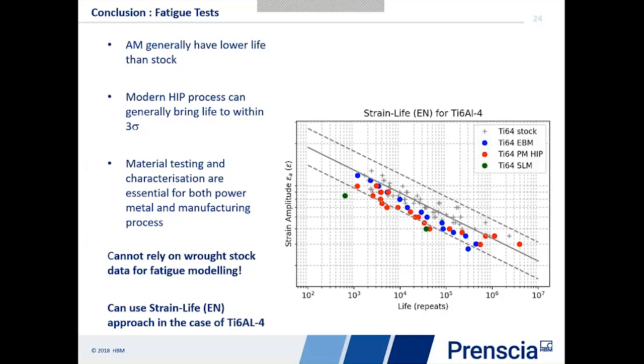At the beginning of this, we went into the analysis thinking that there was probably 3 cases. The best case would be that we could use EN or SN techniques. But failing that, we'd look at initiation from porosity and imperfections as being an approach. And if that didn't work, we'd probably look at using an approach based on composites type analysis, where we treated it as a composite material. But from this, we find that hipping and those heat treatment processes at the end are making it far more homogeneous as a material, where we can use isotropic properties, and in this case, use a nice strain life approach and treat it pretty much as any other material, albeit the curve is different.